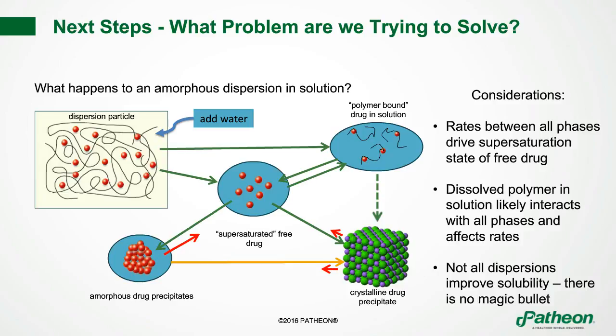And there's a third sink to the drug as well, and that's the intestinal lumen. So what you want to see is the supersaturated drug then absorbed into the system, and that's actually how dispersions that work actually perform. They create this supersaturated state. The polymer maintains the drug in solution, inhibits precipitation, inhibits amorphous drug precipitates, and allows for free transfer of the supersaturated drug into the intestine through the lumen in the jejunum and the duodenum of the body. And that allows for an enhanced solubility, which allows for an enhanced permeability and bioavailability of your drug in the system.